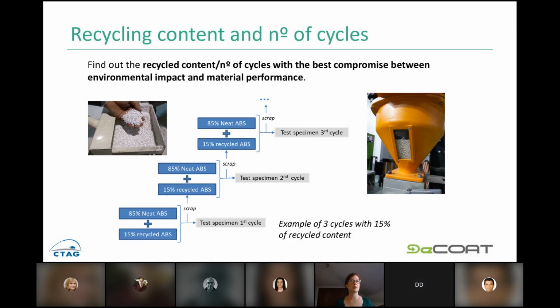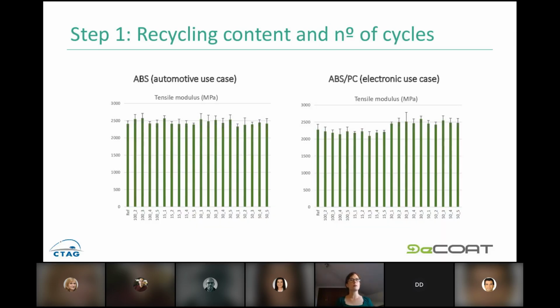The first step is, for example, three cycles with 15% of recycled content, but we carried this out with all the combinations of recycled amount and reprocessing cycles. And these are the results. We assess two use cases: the automotive use case, which uses ABS, and the electronic use case, which uses ABS-PC. Regarding the tensile modulus, you can see that, strangely enough, we don't have a huge impact on this property due to the recycling, both for the amount of recycled content and the number of cycles. There is variability in the data, but the first column is the reference, the virgin material, and you can see that we are reaching very good results in this sense.